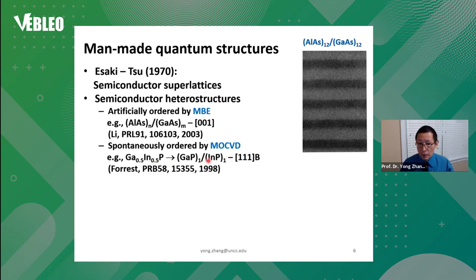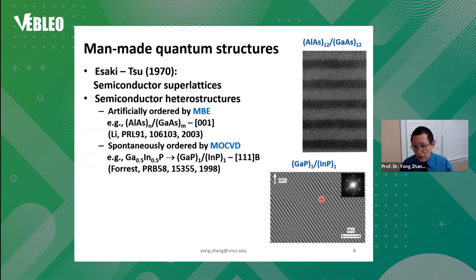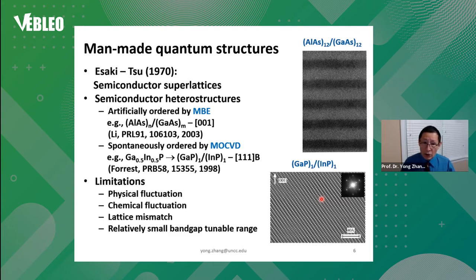For instance, if you want to make semiconductor alloys with a 50-50 mix between the two, you actually end up with what you call monolayer superlattices. You have bright and dark regions, but actually they are not perfectly ordered superlattices — you always get some mixing. The best you can get is probably 80% on one side and 80% on the other side.